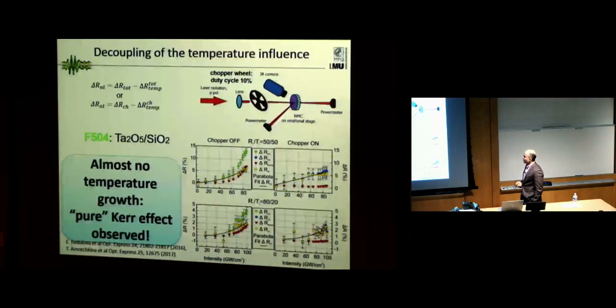To avoid the temperature effect and the thermal effect, we do the following experiment. We introduce a chopper, and we set the chopper to 10%. That means we don't send the same average power, we send just 10% of our previous power. In this particular case, the green dots show the same curve as in the previous case, without the chopper. And when we introduce the chopper, we measure the yellow curve. This yellow curve is purely the Kerr effect, the change in reflectance due to the Kerr effect.